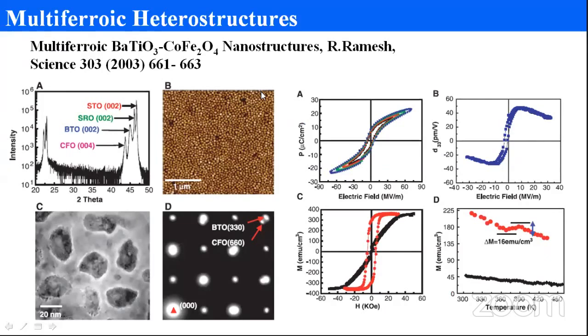Okay, so this is one of the earliest reported multiferroic heterostructures, published in 2003 in Science by the famous group of Ramesh: barium titanate and cobalt ferrite epitaxial thin films. This shows the X-ray pattern of this heterostructure. This is the substrate peak, and then strontium ruthenate, because they are going to measure the conductive property. For that, they put a thin layer of strontium ruthenate, over which they deposited barium titanate and cobalt ferrite.